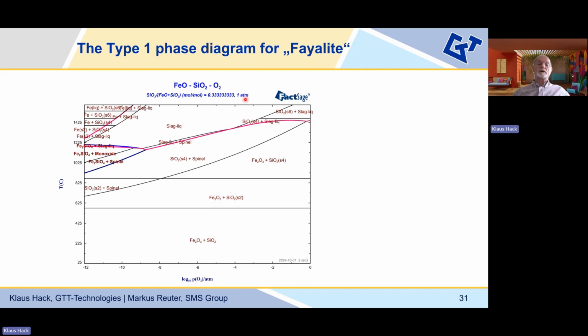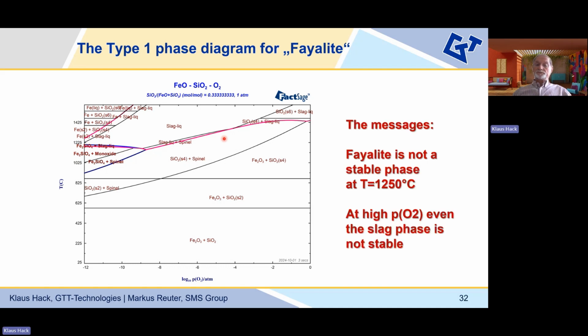Okay, so this fayalite composition with respect to the iron to silicon ratio, that is given here. Yeah, but then when we increase the oxygen partial pressure, we leave the range of liquid slag. We come into a range where the oxides at the high temperature are all solids. That is now very important to keep in mind, because we will see later that this change of having a high temperature liquid into a high temperature phase combinations of stoichiometric solids, that makes a big difference, right? So the message from the phase diagram is the fayalite is not the stable phase that we are interested in.